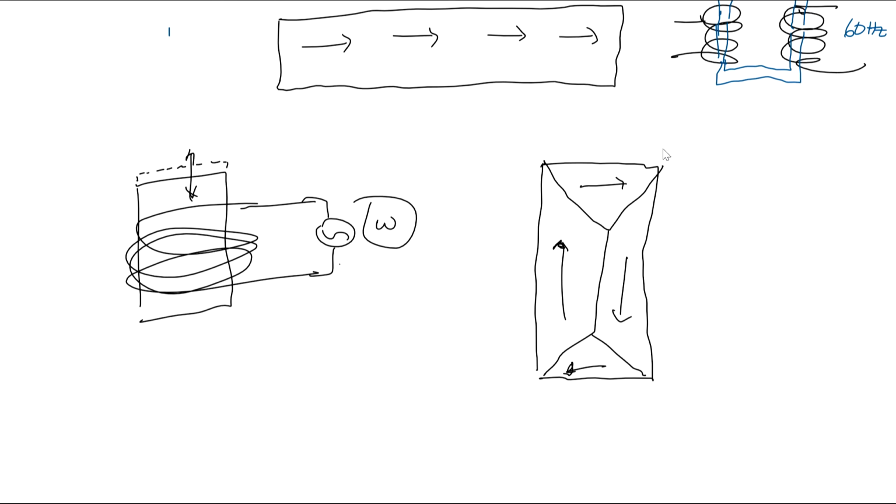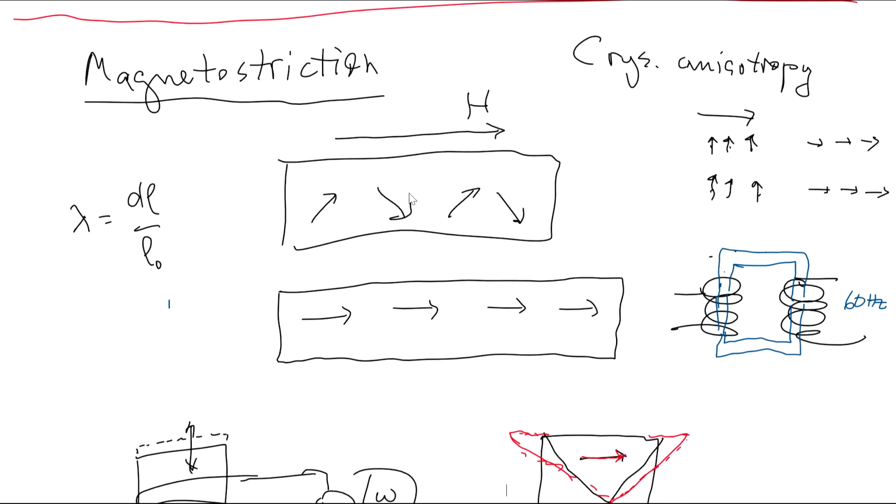So the domains themselves, if we subject this magnetic domain to, let's say, an internal magnetic field, it would want to be elongated along this axis. And naturally, because the area is magnetized that way, the natural domain would be bigger, implying that following this magnetostriction effect, when it's all magnetized in this direction.